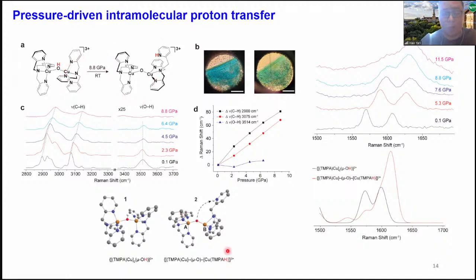We can actually model these structures and obtain a stable structure using DFT. Now, the interesting thing is that this compound, once generated, is actually metastable. We can take it out of the diamond cell, keep it in the glove box, it stays there for a couple of days. So this really allows us to do a lot more characterizations.